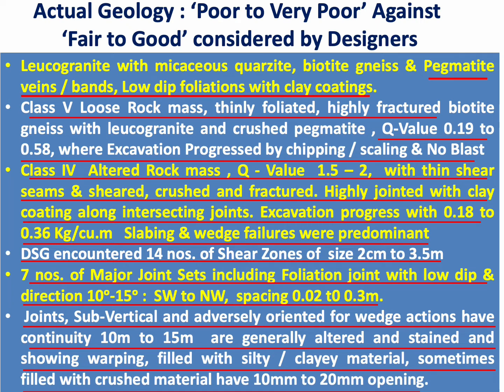So in all, the downstream surge gallery encountered 14 numbers of shear zones or shear seams, which were ranging in size from 2 cm to 3.5 meter in thickness. There were 7 numbers of major joint sets, including foliation joint, which was low dip, had a direction of 10 degree to 15 degree, southwest to northwest, and the foliation spacing was 0.02 to 0.3 meter.